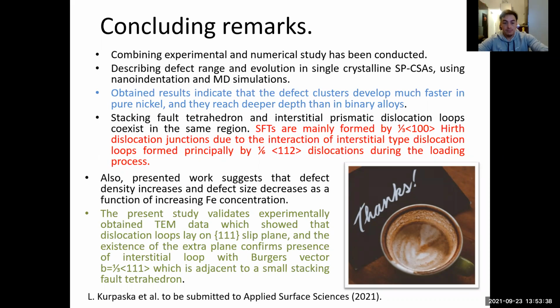Yes, exactly. Okay, so I was actually looking at the same material system, and something I found really interesting is that everyone always talks about sluggish vacancy diffusion. But something I observed, and I've been wondering how this affects larger defects like these stacking fault tetrahedra, is that the distortions in the lattice create both barriers to motion and also shortcuts to motion. They're like high mobility tracks that vacancies will zoom between. I've been wondering if that makes any effect on defect consolidation, or if it's just making small isolated clusters. Well, not here, because this is low temperature.